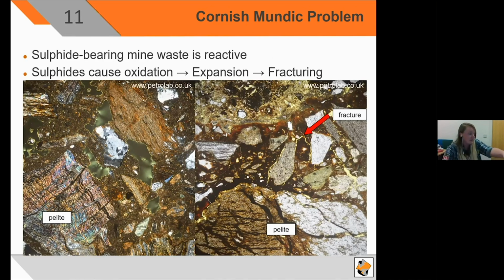So in this one on the left, this is our typical mine waste, which is a pelite. It does look similar to the phyllites. However, a pelite is formed of fine-grained clays rather than a phyllite, which is slightly higher recrystallization, and therefore you get coarser micas. But essentially similar premise. So on the right, you have the big reddish brown oxidation going through the binder, radiating out from that pelite. You get an associated fracturing, expansion, and again, blows apart, exactly the same premise.